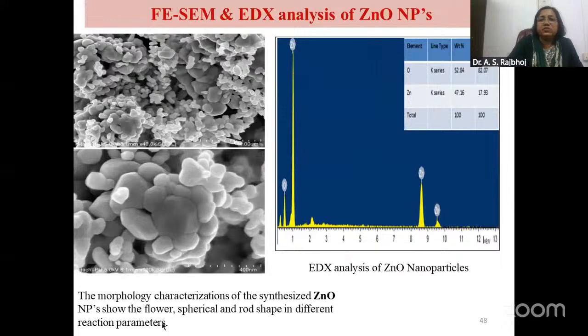Then we have done the characterization by SEM and EDX. You can see here the shapes when we do scanning electron microscopy. We found flower-like shapes, some are spherical, and rod-like shapes are also being formed. When we did the EDX analysis, you can see the graphs show only zinc and oxygen, and if you add the totals, it comes to 100. So we say that the EDX analysis shows that the nanoparticles synthesized by the electrochemical reduction method are found to be highly pure in nature.